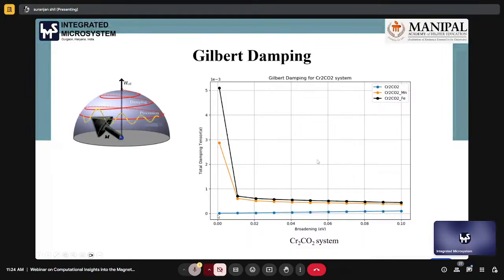And what you see when we have undoped materials is that this curve is not completely stable, but compared to this there is less fluctuation. But when we dope with iron and manganese, we can see that the magnetic Gilbert damping tensor increases, and if we go to the higher broadening zone, there are no such changes. So at the lower broadening zones, we can see the changes, which signifies that if we dope some other atoms into the chromium carbide MXenes, we can change the stability of the magnetic state.